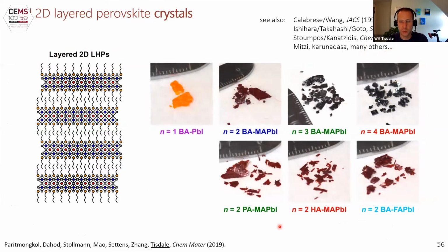Since working with the colloidal nanoplatelets, we've also begun doing a lot of work with solid crystals of the layered structures. So rather than going a colloidal route, you can directly synthesize large ordered layered structures of these 2D organic, inorganic halide perovskites. They form extended networks like this that have a very well-defined crystal structure.